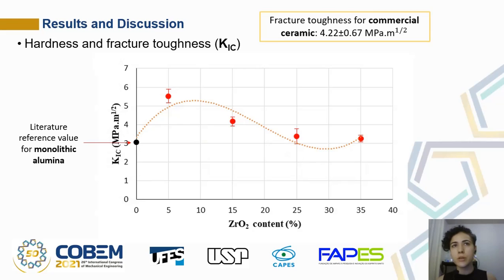The results also show that the addition of zirconia in alumina matrix promoted an increase in fracture toughness up to a threshold value. There was a drop in this property with additional zirconia content, and using a reference value of fracture toughness, a parabolic behavior for the curve can be noted. The higher value of this property was obtained for the 5% of zirconia volume fraction.